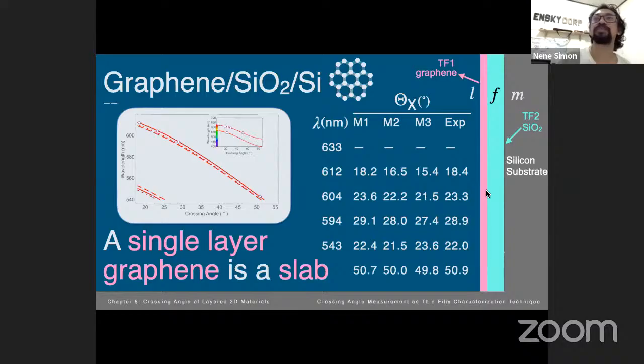And if it's continuous, and if it has a finite thickness, it means that Fabry-Perot resonance can occur within the graphene sample. And lastly, since graphene is characterized by the refractive index N, it means that the real part of the electric permittivity plays a role in the optical interaction of graphene, which is not assumed when it is treated as a perfect conducting sheet.